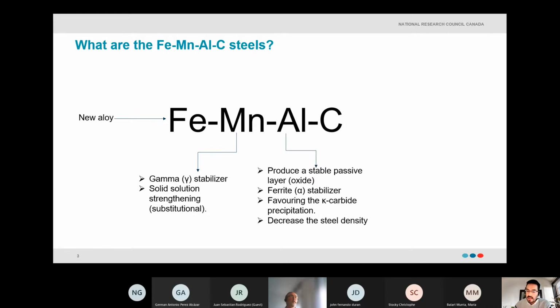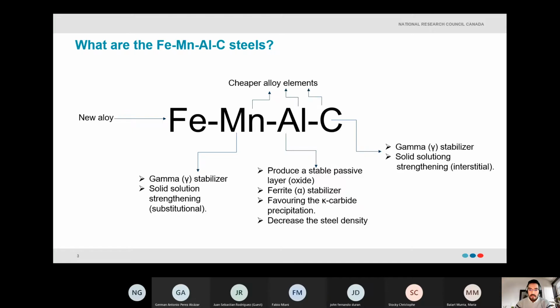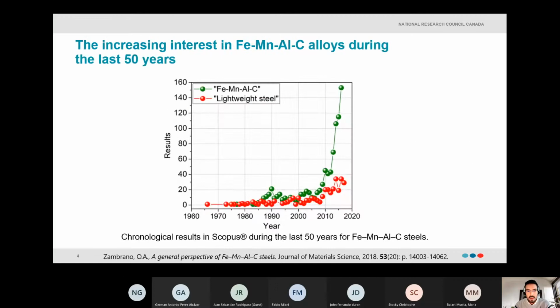The aluminum in this case produces a stable passive layer similar to chromium. Aluminum is also a ferrite stabilizer, favors the kappa-carbide precipitation, and due to its very low density, of course, it will decrease the steel density in a remarkable way. And carbon is a gamma stabilizer and a solid solution strengthener in the interstitial way. But the main difference with conventional alloys is that manganese and aluminum are cheaper alloy elements, and that is really important in the market.